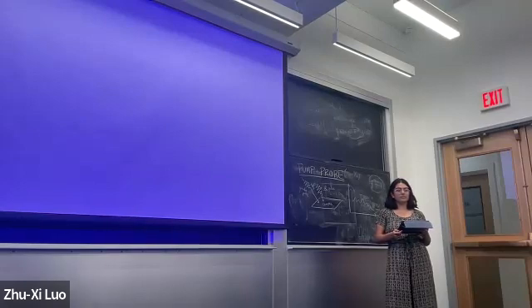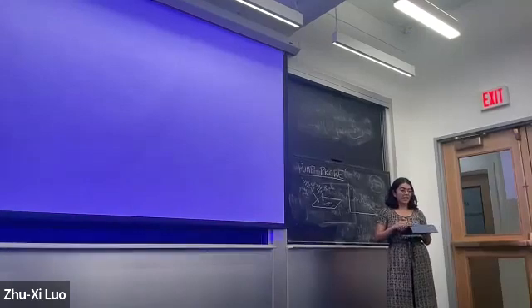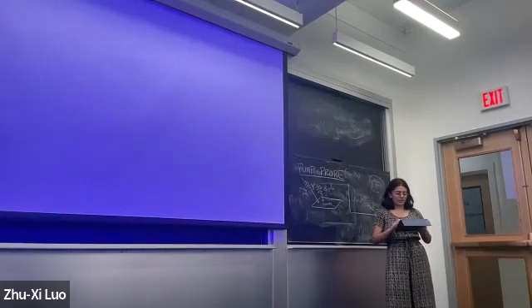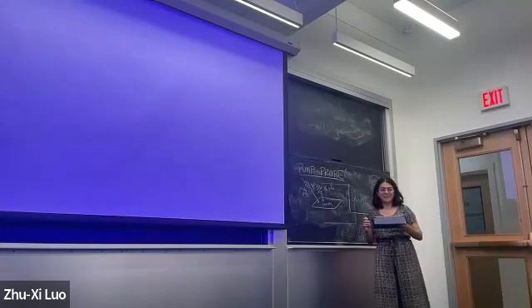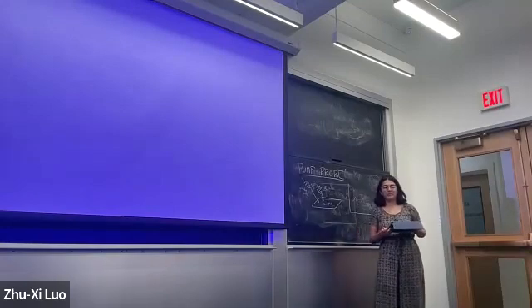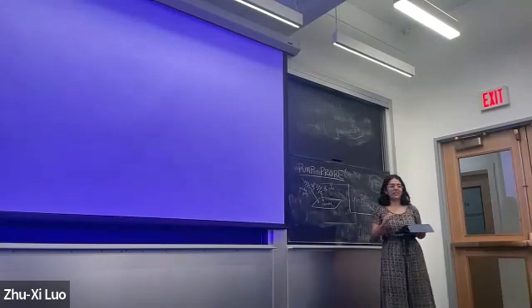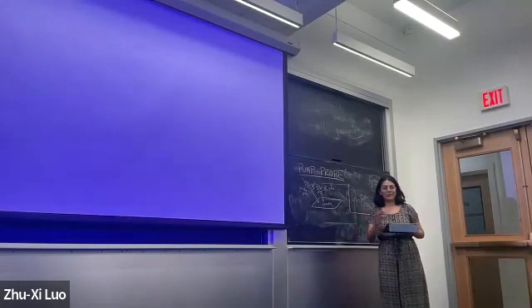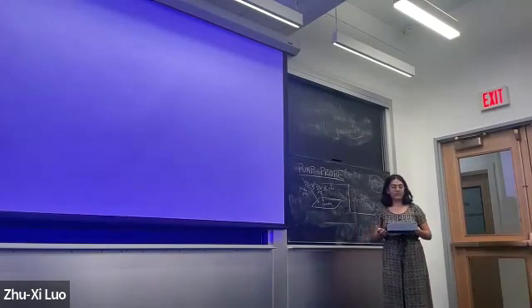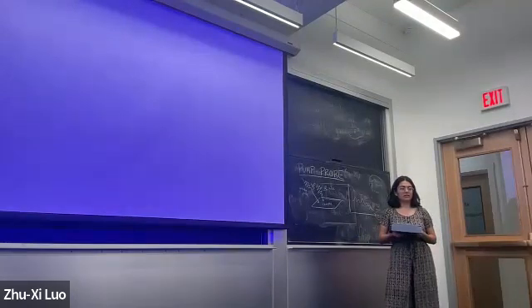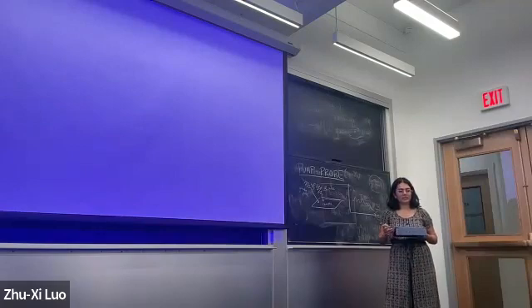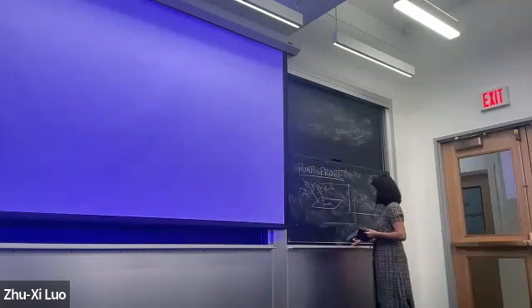One thing that one can do to improve on this scenario is to apply the pulse to the tip, and then use the tip to focus the pulse yourself. Yeah, so it's exactly like time resolved STM, which is a nascent experimental technique. People are trying to get more spatial resolution, but for everything I'll talk about today, it's generally uniform over the sample. And also sometimes I've heard the concept called near field.